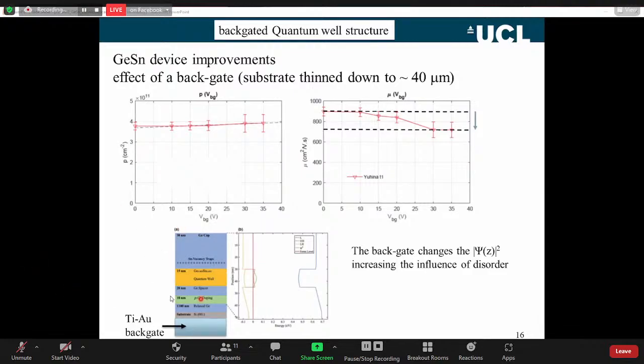that we tried to make, the so-called backgate device, where we take the wafer and we mechanically thin down the substrate and then attach a titanium gold backgate. So we can use that backgate as a back electrode. We thought we could control the carrier density of the quantum well. We thin the substrate down to about 40 microns. It does mean that you've got a rather thick substrate still, but you need quite a lot of voltage here to change anything.